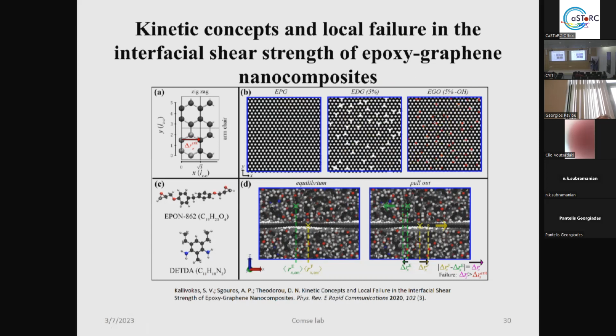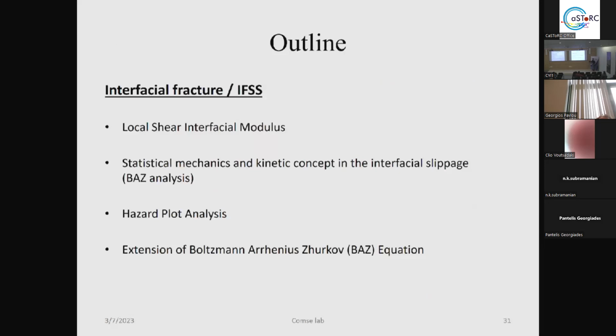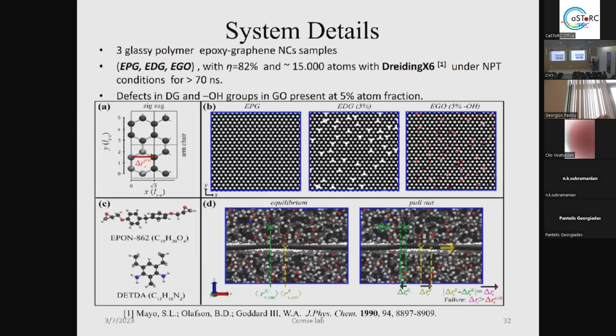And the main target of this research was to calculate the interfacial fracture, or what the people doing fracture mechanics call the interfacial shear strength. So we took these three different systems at 82% crosslinking degree, with bigger systems this time of more than 15,000 atoms, with Dreiding exponential-6 as a force field, and we equilibrated for more than 70 nanoseconds with NPT conditions.